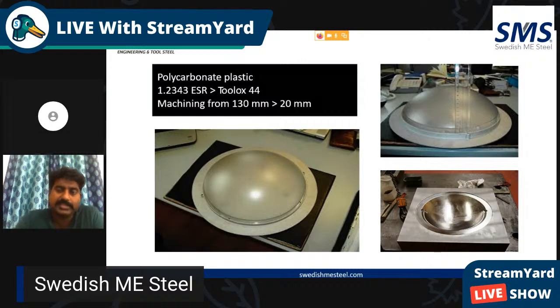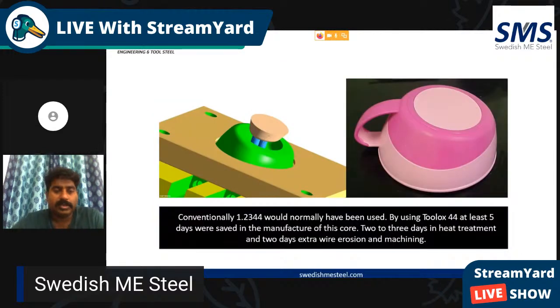It is a 45 HRC material which has a unique combination of both high strength as well as high toughness values, and it has homogeneous properties throughout the length and breadth of the plate. So you need not worry about the quality of the material. So conventional 1.2344 would normally be used, which has been replaced by Toolox 44, saving 2 to 3 days in heat treatment and 2 days extra wire erosion and machining.